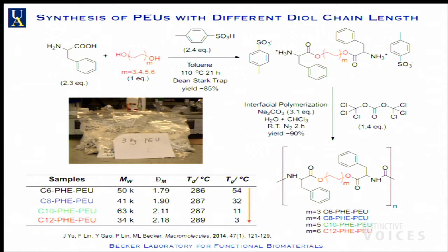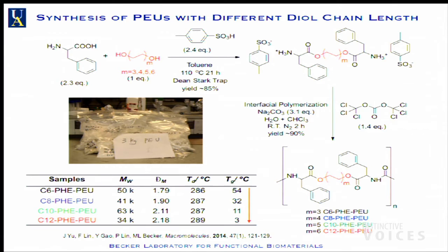This is the same way they make polycarbonate and lots of polyurethanes. It's called a step growth polymerization. Very common, and amenable to multi-ton manufacturing in single batches. The point I want to make here is that C6, C8, C10, and C12 is just the length of this diol. So you can control the mechanical properties, the hydration, and the degradation by changing the length of this diol, so that you have something that starts to get flexible at 50 degrees C, which is the material we'll focus on today, and softens to sub-physiological temperature and then sub-room temperature. So from something very rigid, hard and tough to something very soft.